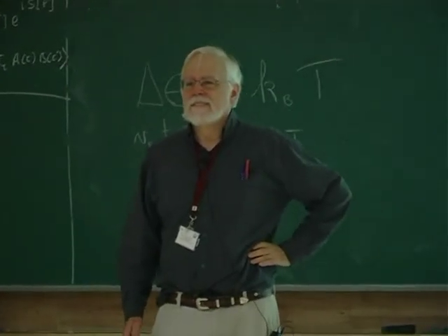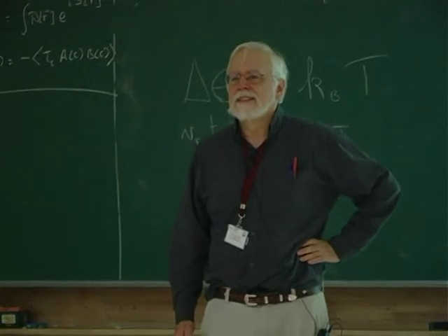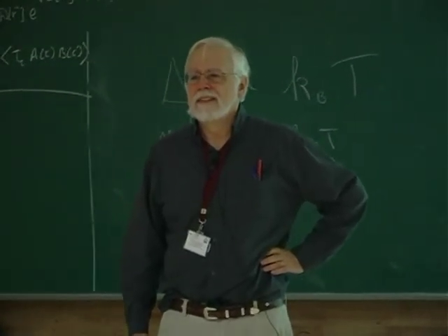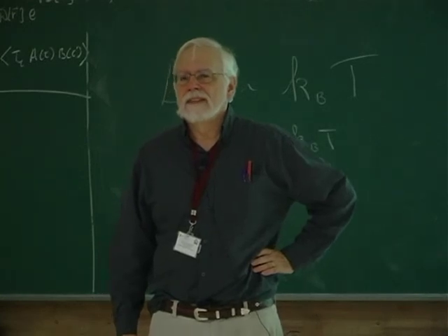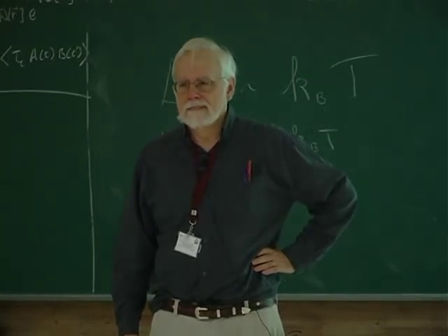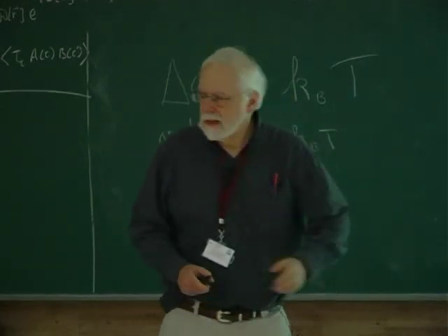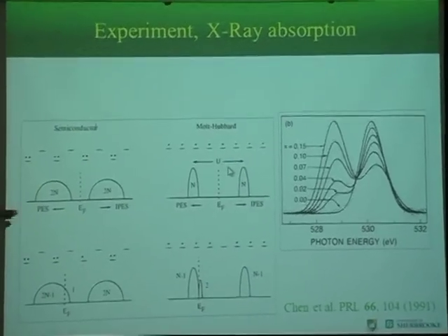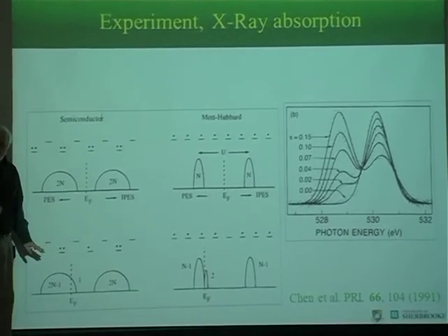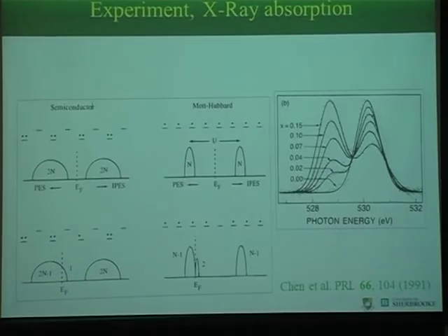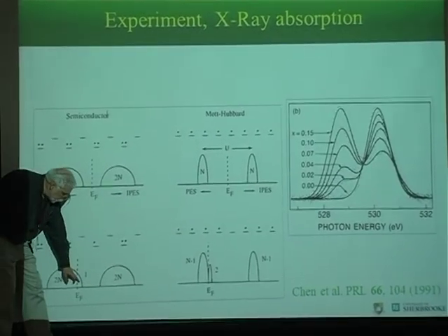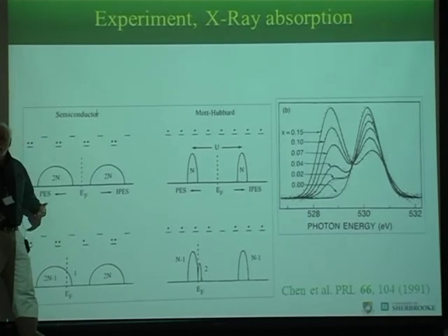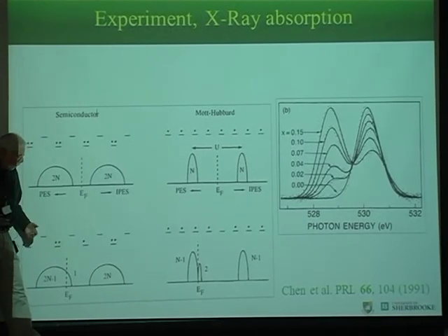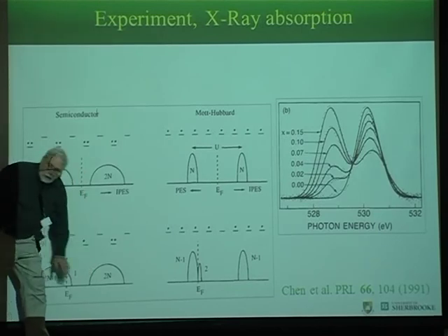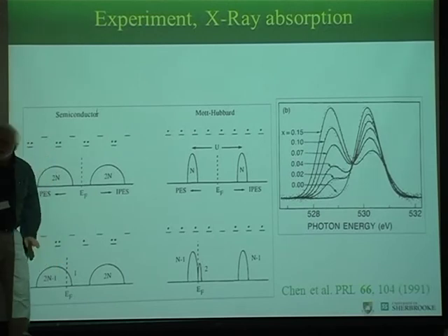In one of the first slides, you showed the photoemission spectra double peaks, and you said it was from the Mott transition and not from a semiconductor, because a semiconductor was also expected to have two peaks. So how can you say that it's from Mott? So in the case of the semiconductor, I also have two peaks because I'm starting from a very deep level, and then I can excite an electron here or there. So that gives two peaks. But if I look at the cross-section, this should be independent of doping, and this should grow linearly with doping.